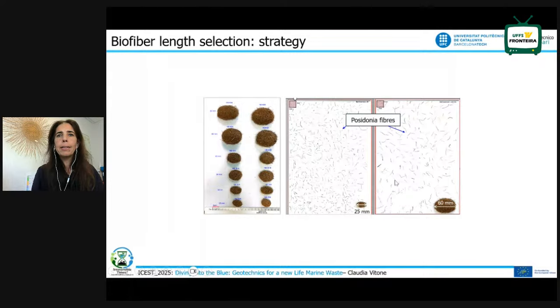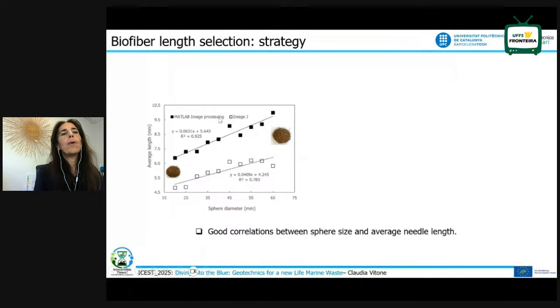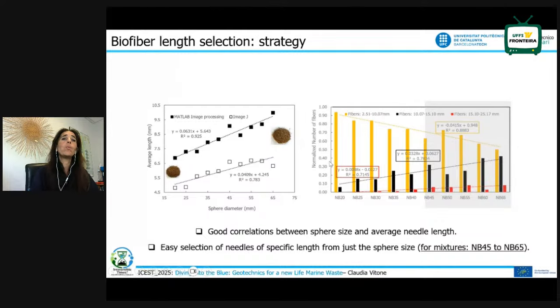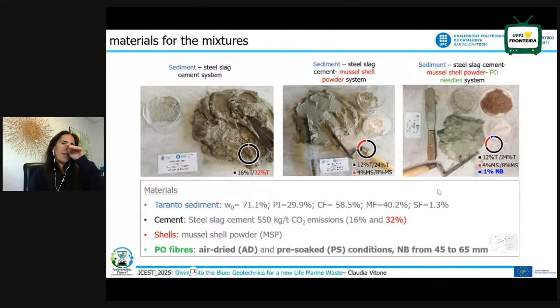We can scan these fibers, and then we have run some analysis to try to understand if there was a correlation between the diameter of the sphere and the average length. Essentially, as you can see, the correlation is very good, in particular when you use MATLAB. And what does it mean? This means that by just selecting the sphere diameter, we could have an idea of the average length. Then we went in deep, because we also have understood that there is also a correlation between a group of fiber length.